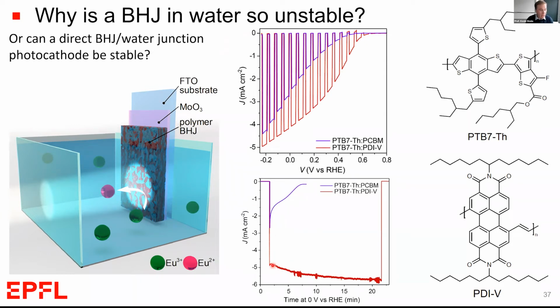We see, in fact, a slight increase of the photocurrent over these 20 minutes, and that's probably due to the water which starts to ingress a little bit into this material, increasing the surface area. But nevertheless, a huge change in the stability in this sacrificial type system, which suggests that correctly choosing the molecular structure of these organic semiconductors is really important for getting stable photoelectrochemical performance.